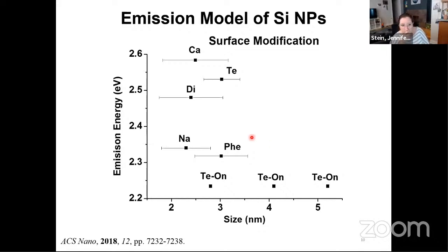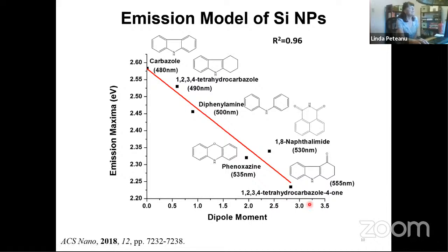So basically, this shows a plot. If you try to look at the emission energy in eV and you have various ligands that we've abbreviated here, and you try to find any trend, you basically won't find one. And this is the publication, this is summarized. However, if you plot against the calculated ground state dipole moment of the ligand, you get a very nice correlation and a predictive correlation. In fact, we synthesized a new system based on a different ligand, and took other data from the literature just to show that this was actually a good correlation.